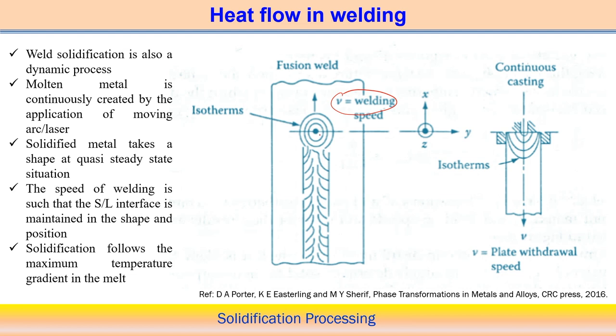So here you can see that suppose V is the welding speed, and at a particular instant of time this is the application of the heat flux from the arc. The arc creates some isotherm and then it continuously moves, and behind this there is continuous solidification. The rate of solidification tries to comply with the velocity of the heat source, assuming a uniform velocity of the heat source in one particular direction. This is the most ideal situation in a welding process, and the weld pool takes a particular shape